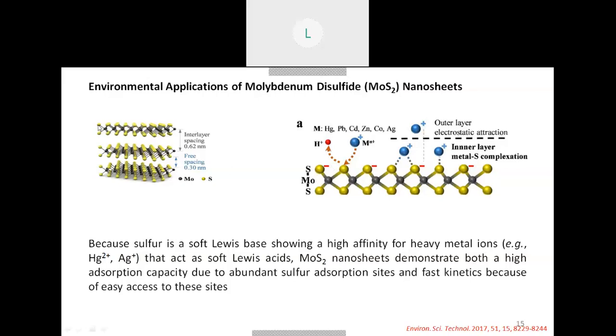Because the surface is functionalized with the sulfur atoms, they act as a soft base, where the metal contaminant can be removed. So this is the mechanism. This is where the sulfur layer is negatively charged and able to replace the hydrogen atom from it, and the metal can be adsorbed directly over the surface. So there can be two mechanisms. One is the outer layer electrostatic attraction. The other is metal-sulfur complexation.